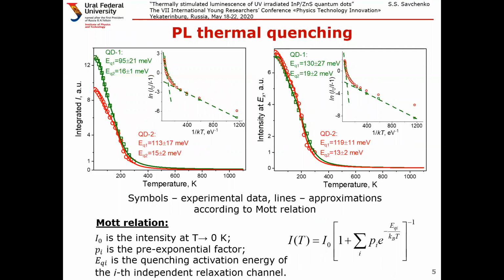Thermal quenching was analyzed for the exciton and integrated intensity. Arrhenius plots demonstrate that the quenching processes are caused by the presence of at least two non-radiative relaxation pathways. Approximations by the Mott relation with two channels give the shown energy barriers. Comparing these graphs, we can see that the defect-related band affects PL quenching stronger in smaller QD1 nanocrystals.